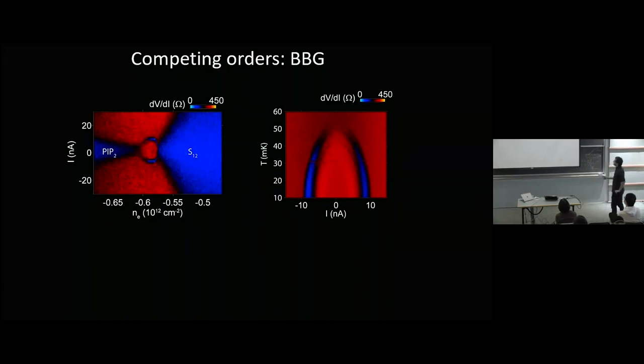Okay? And this is also a phase that seems to show up at very similar temperature scales to the superconductor, and it's right in the same spot where the superconductor is. It's in between the same two phases. We don't know what this is, and it doesn't really make much sense to me because I would have thought, let's say you have competing singlet and triplet superconductors, whichever one dominates should win, and maybe you'd have a transition from a singlet superconductor to a triplet superconductor with in-plane field as you suppress it, but in fact, that's not what happens. You don't have superconductivity at zero field, and we don't know why.